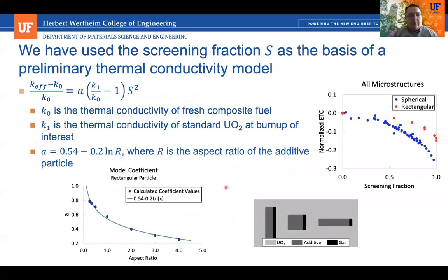So we're going to use the screening fraction, and we've developed a model. We can normalize the thermal conductivity by the fresh composite fuel. And now we get the thermal conductivity to collapse onto each other even more, but we still have a distinctive curve for the spherical particles and for the rectangular particles. So we've come up with this model, which is the normalized thermal conductivity as a function of the screening fraction squared. And then we have K1 over K naught, where, sorry, K naught is the thermal conductivity of fresh composite fuel, and K1 is the thermal conductivity of standard UO2 at whatever burnup of interest that we have.